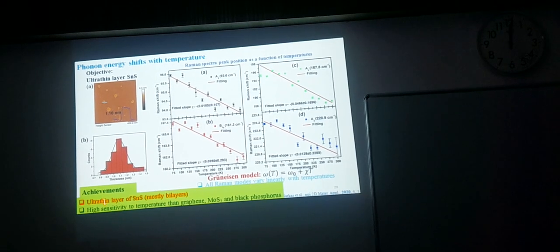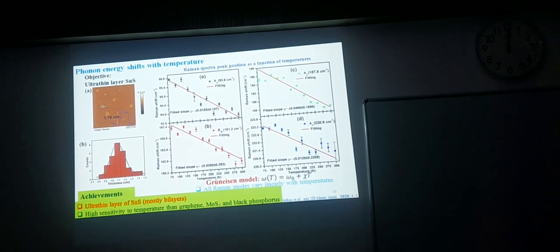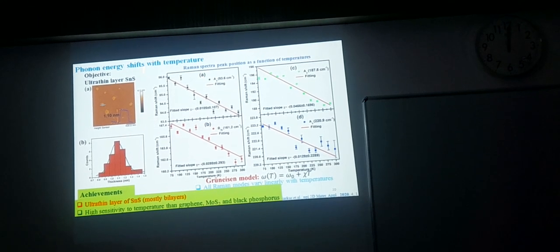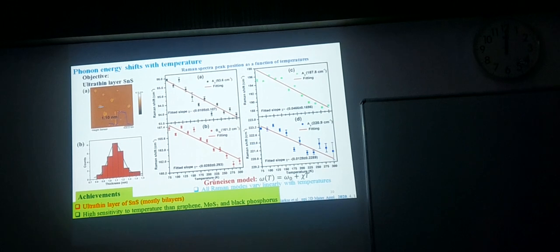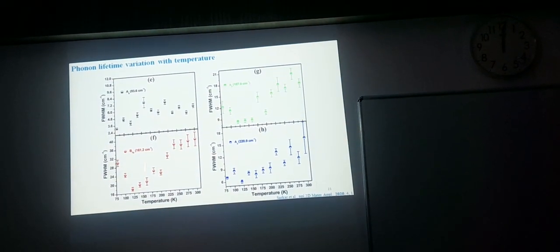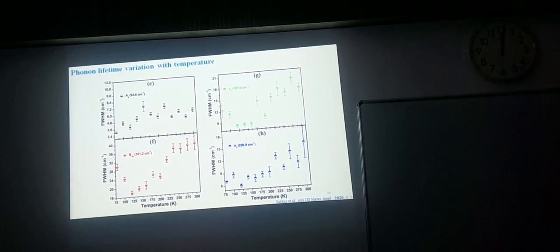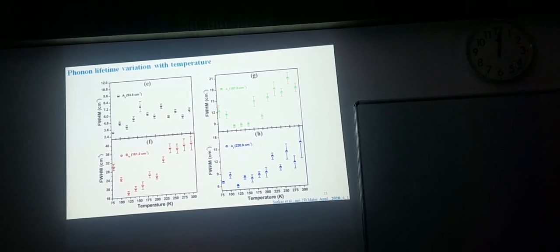So here you can see the sheets are very small in size, around 1.2 nanometer thickness, and the lateral dimension was a few micron. So here is how this phonon energy shifts with temperature. We studied the first order temperature coefficient here, and also the phonon lifetime. So you can see how this phonon lifetime is changing with the temperature. I will not go into the hardcore physics here. We reported it the last time.